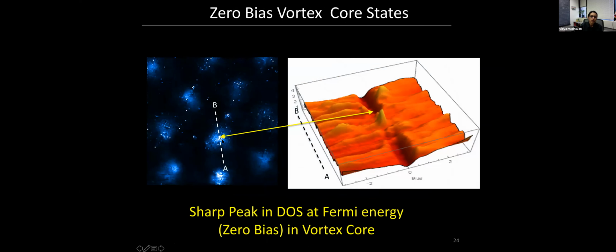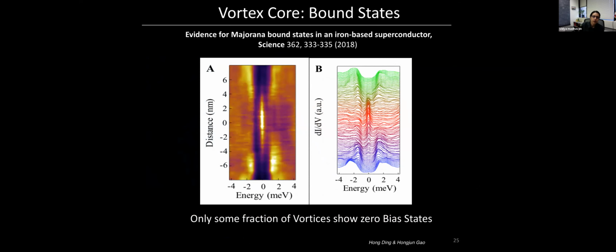And if you look at one of these vortices, take a line cut across it, here's what you see. Here's the superconducting gap far away. And right at the center of the vortex core, you see a nice sharp peak in the density of states at 0 energy. Now, the first people to look at vortices in this system were Hong Ding and Hong-Jun Gao.